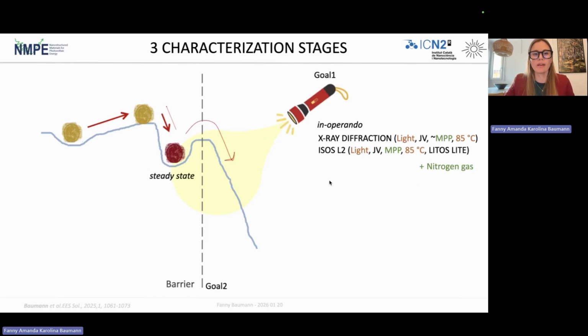We're also going to keep the cells under nitrogen gas flow, at 85 degrees Celsius, to try to reduce the influence of other stressors. Additionally, we're going to do before and after characterization. So we are doing a suite of characterization, including JV curves, impedance spectroscopy, photoluminescence, and time resolved photoluminescence. And we're also going to simulate some of the impedance spectra to see if our observations are in agreement with what we believe is happening. And you can see we have two goals.